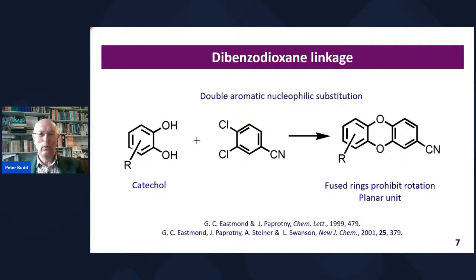Now, the chemistry that we used in creating these networks had been worked out. Aromatic nucleophilic substitution is something that any organic chemist knows about. But Geoff Eastmond, who was at Liverpool University and did a lot of work on polyimide membrane materials, had worked out for small molecules that you could get a very effective double aromatic nucleophilic substitution reaction if you have the right activated species that gave this dibenzodioxane linkage, a sort of fused ring structure. And what Neil realized was that you could apply this to create the sorts of networks that I've just described.